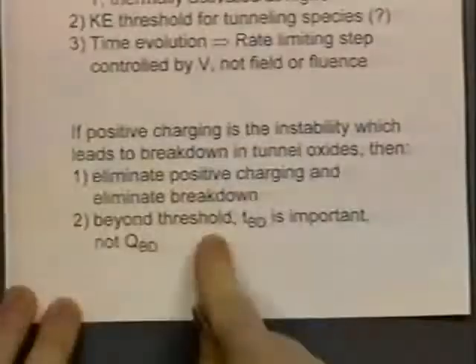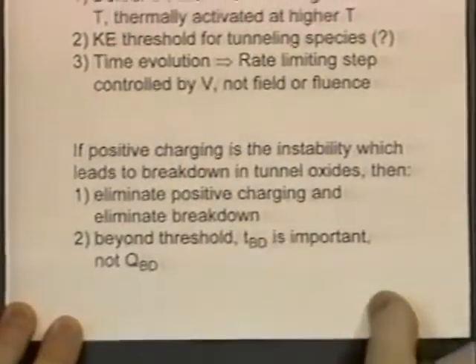So you would see an exponential increase in the QBD, but if this charging is what underlies the breakdown, it's just something that evolves in time if you're above a certain bias. You understand what I'm saying? And so this is a very important point, and we really have to ask the question, well, tell me, Dr. Farmer, is this positive charging related to breakdown? Well, okay.